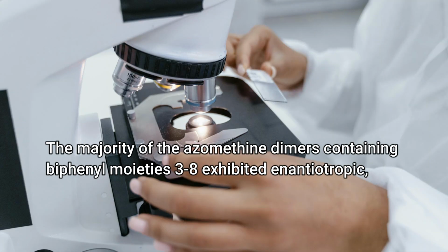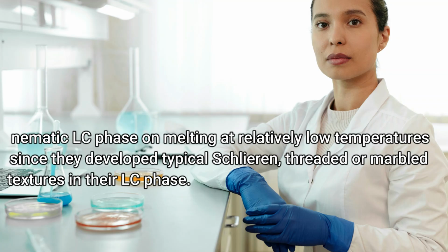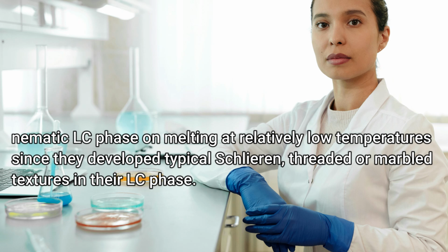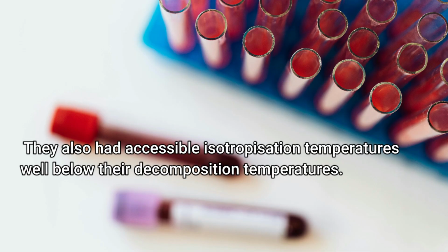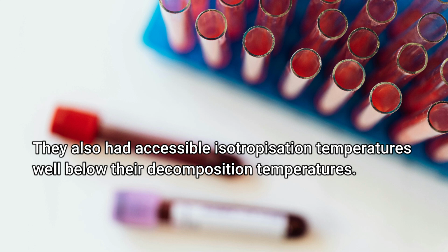The majority of the azomethine dimers containing biphenyl moieties 3 to 8 exhibited enantiotropic nematic LC phase on melting at relatively low temperatures since they develop typical Schlieren, threaded or marbled textures in their LC phase. They also had accessible isotropization temperatures well below their decomposition temperatures.